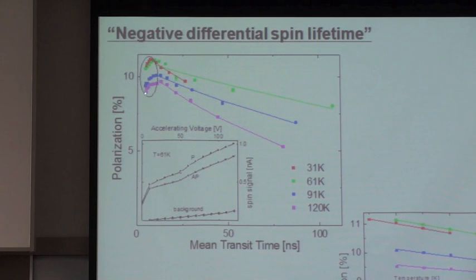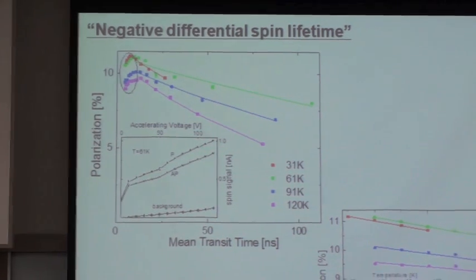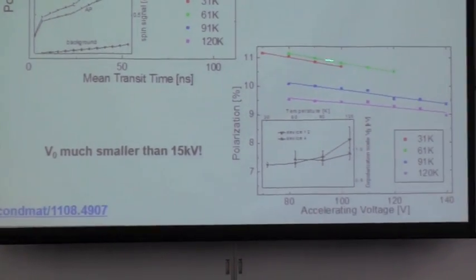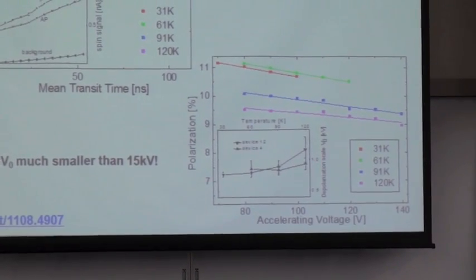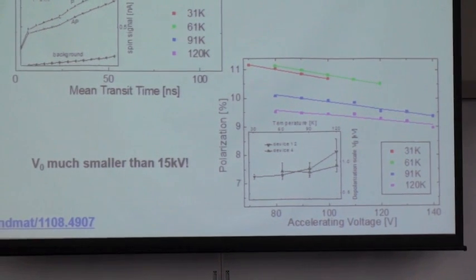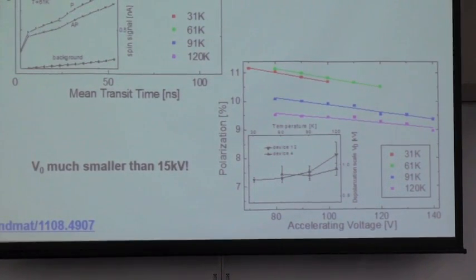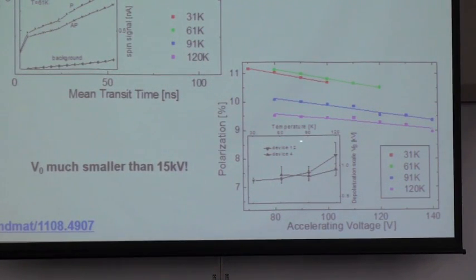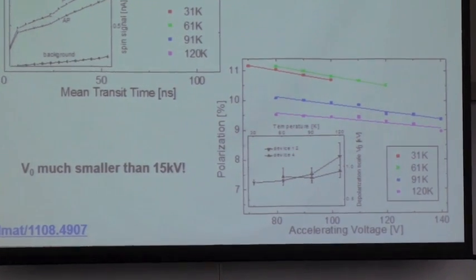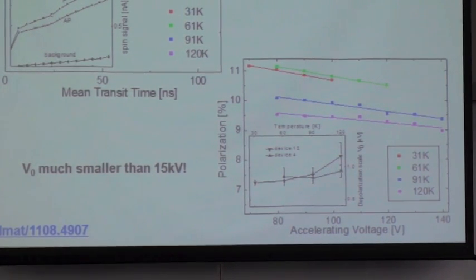If we look at this anomalous regime as a function of the voltage, not the transit time, then you can see we have this quasi-linear regime, which we can compare to our exponential and extract a voltage scale, a comparison to this V0 that I showed you before. And maybe it's hard to read here, but essentially we're measuring a voltage scale on the order of 1 kilovolt, not 15. So the question is, what's going on?